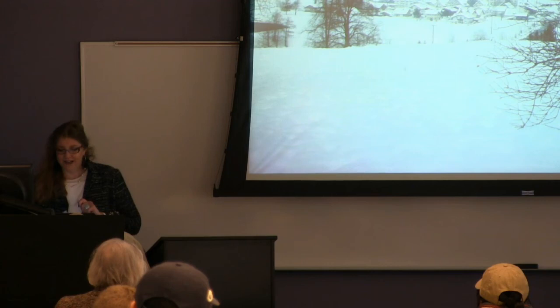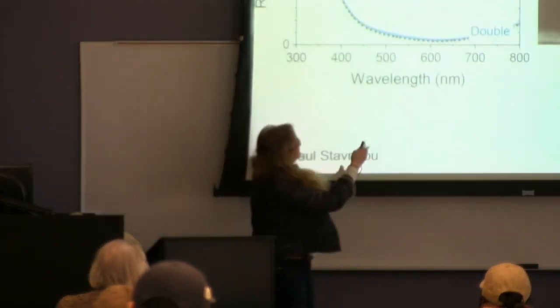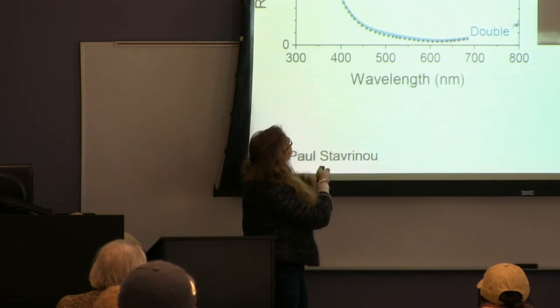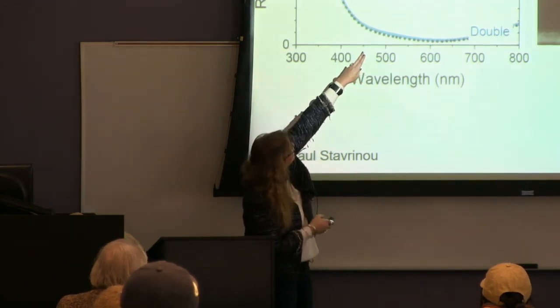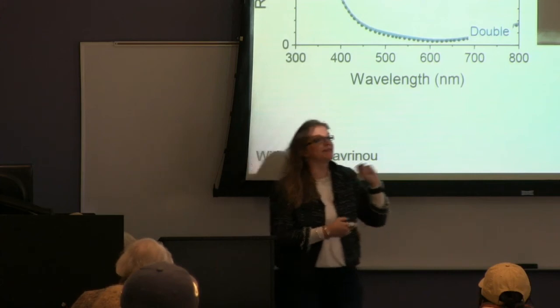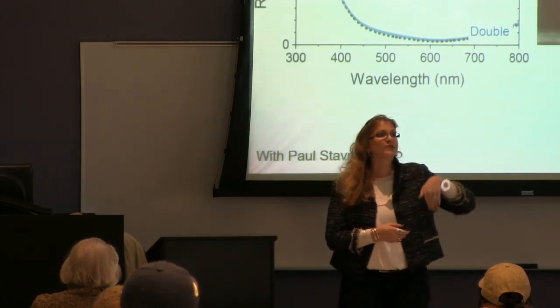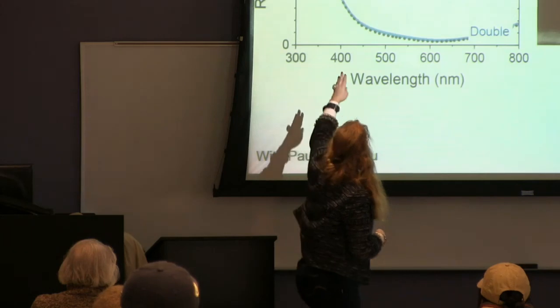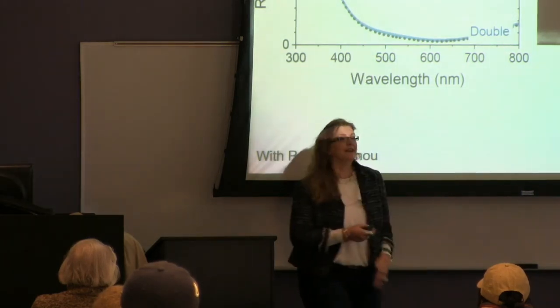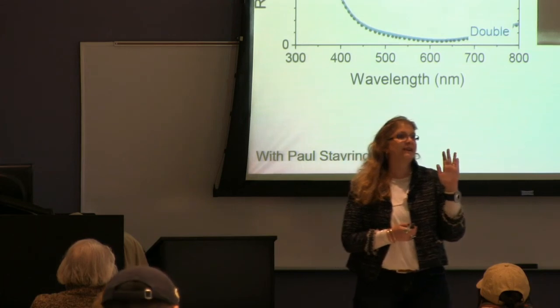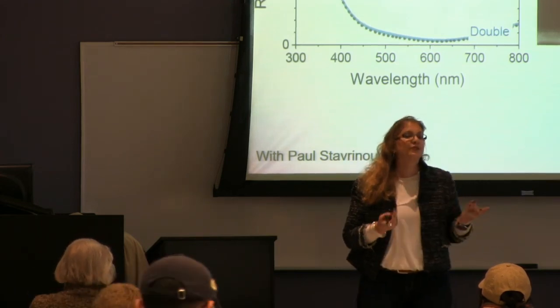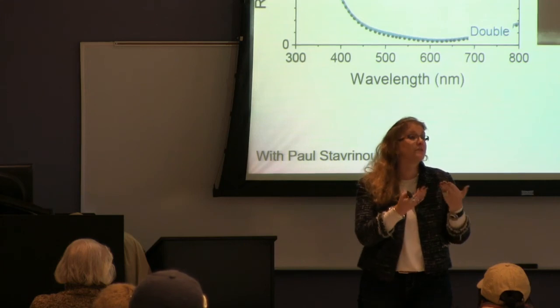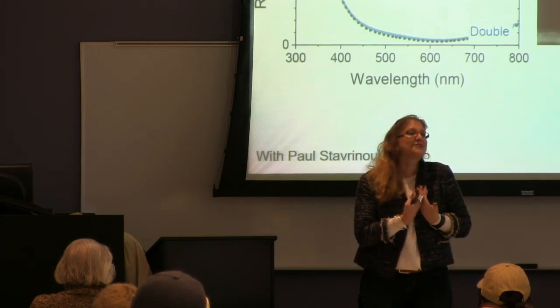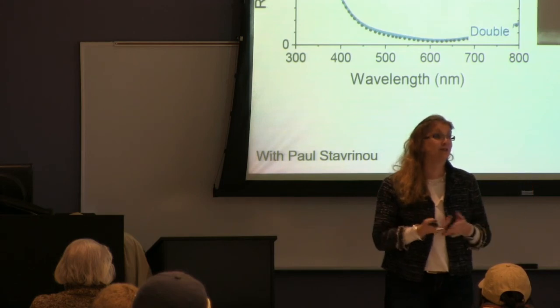So this has an extremely nice optical effect that we can use and we get for free when we make a very simple cavity on that side. So you see the white part in the middle is the glass slide. You dip it in, you get the coatings on both sides. We can prevent that, like what we did over here for this one, just by putting a cover layer on the other side that we then rip off. But most of the time, it actually helps us, especially for heat mirror applications, because it's easier to make 40 layers, since in principle you only have to make 20.